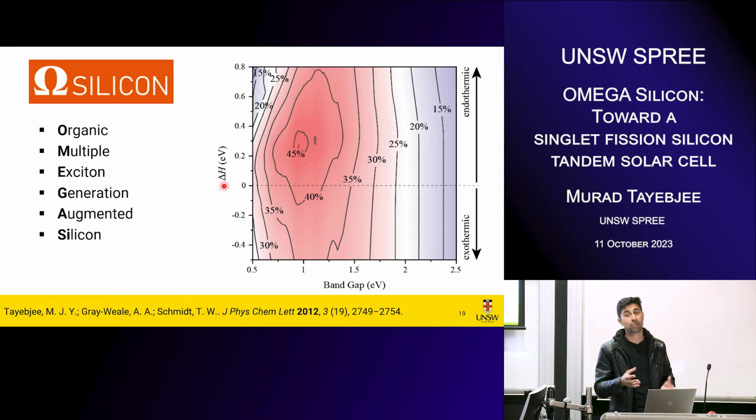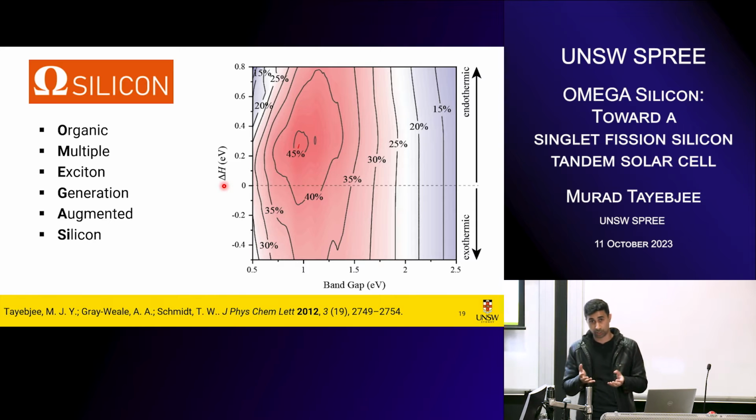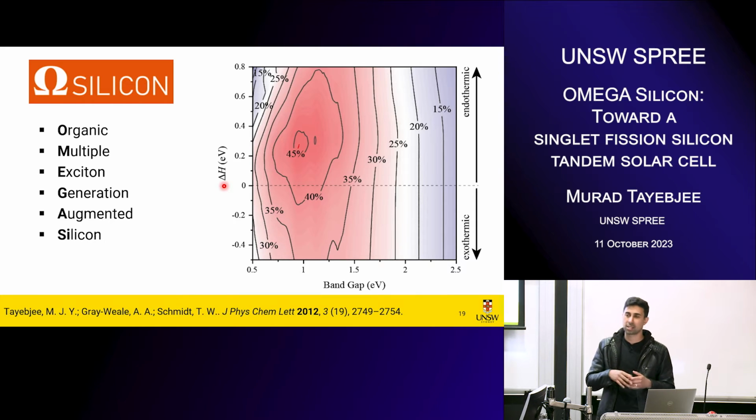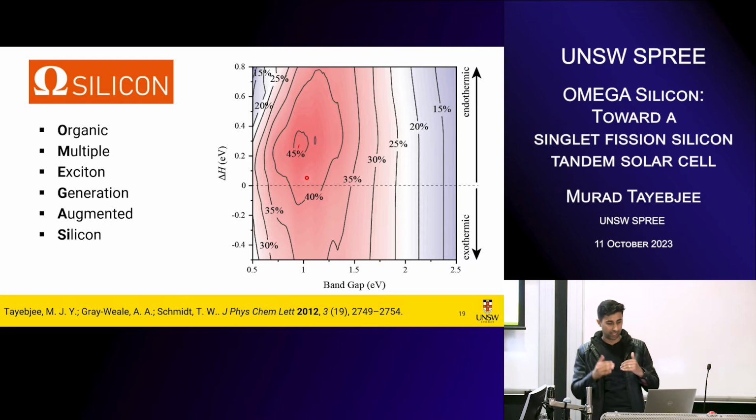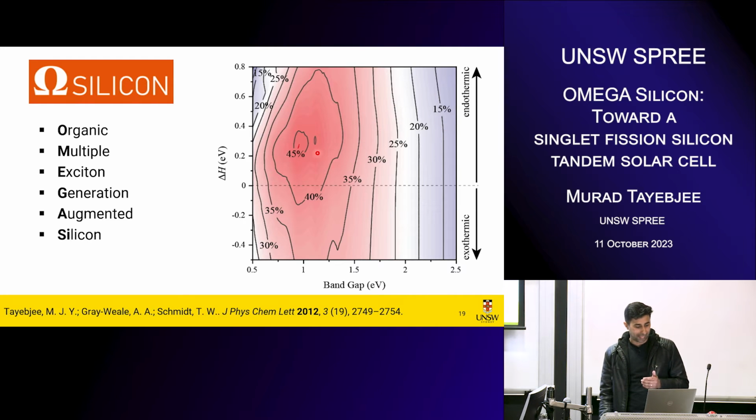So for instance, in tetracene, which is the fruit fly molecule for singlet fission, it's about 200 meV endothermic. So actually our limiting efficiency is above that isoenergetic singlet fission effect where your triplets are exactly half the singlet energy. Yeah, so it's actually interesting that we could utilize that entropy to generate a more efficient solar cell.